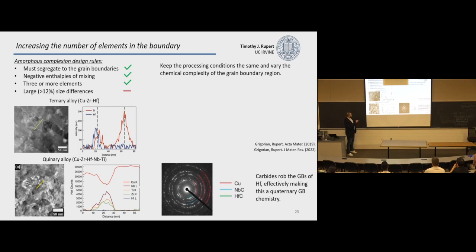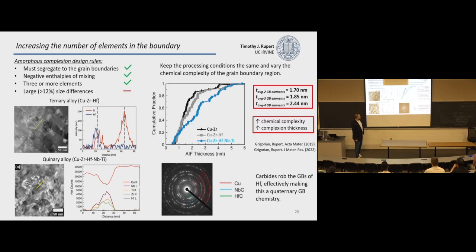We have a 3-element alloy and something with 4 elements at the grain boundary. But what you can do is then go and see if you have amorphous complexions, but more importantly, go and measure the distribution of the thicknesses of those amorphous complexions. So we go in and we measure about 50 of those amorphous grain boundaries, measure the thickness, and we make